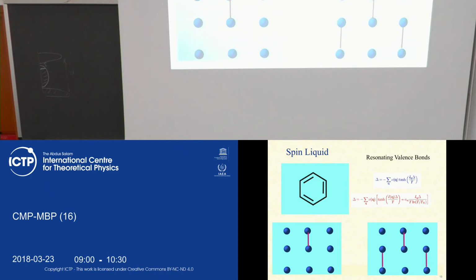And moreover, one can use the same ideas which I just explained for high temperature superconductivity, namely the resonating phase. So the Kondo effect, as I said, on one hand is a localized effect which leads to an increase of backscattering, and at the same time it screens the local moment. This is another phenomenon which is well understood and known, that the Kondo effect produces screening of a localized moment. On the other hand, it's related to the possibility to flip spin.